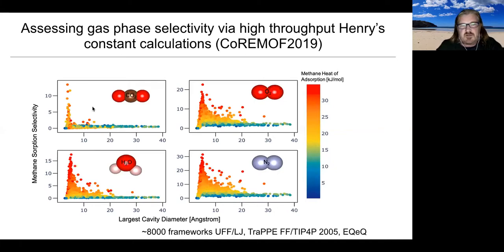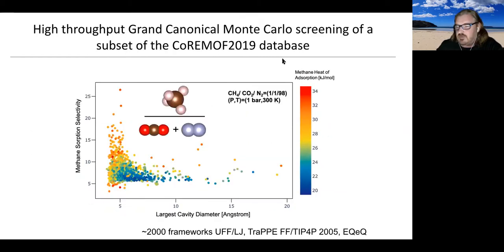So that's selectivity of methane against individual components, and we can then do grand canonical Monte Carlo calculations and compare a real mixture of methane, CO2, and nitrogen in this proportion, and we find something which is broadly similar to what we found before. This is now a subset of the frameworks we were looking at before. Again, methane adsorption is important, and we do require relatively small pores within our materials.